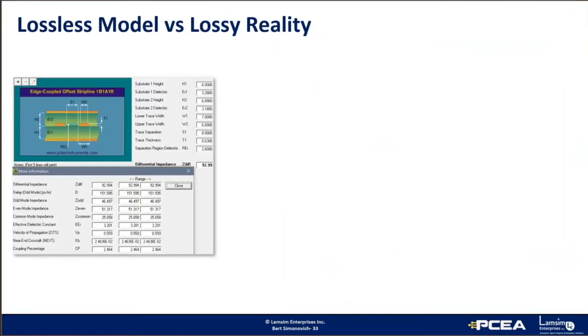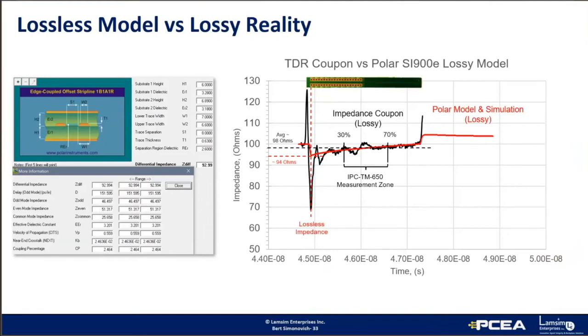So here's the issue. We design the stack-up, then we do our SI modeling analysis based on the stack-up parameters. Board shops use the TDR to measure characteristic impedance. But more often than not, it's not what was predicted. This is because the 2D field solver only calculates the lossless characteristic impedance of the cross-sectional geometry. It has no input for conductor resistivity, dielectric loss, or how long the conductor is.